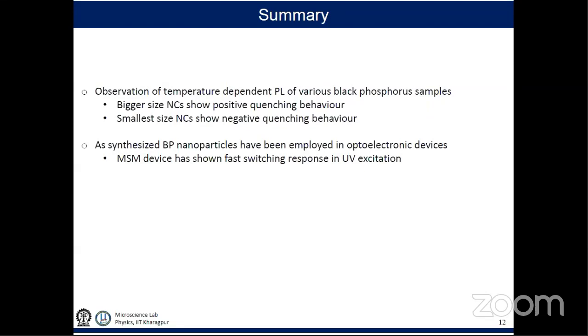In summary, we have successfully synthesized black phosphorus nanocrystals using a simple sonochemical method. We have employed these phosphorus nanocrystals in a photo detector device. It is basically a UV photo detector, where the detection was done using 325 nanometer laser excitation. The bigger size nanocrystals have shown normal thermal quenching behavior, but the smallest size nanocrystals have shown negative thermal quenching behavior, that is attributed to the attachment of various surface functional groups, oxygenous surface functional groups.